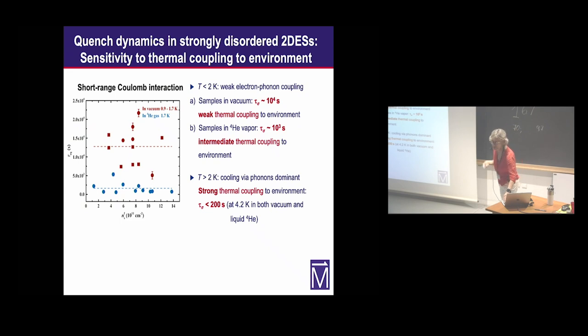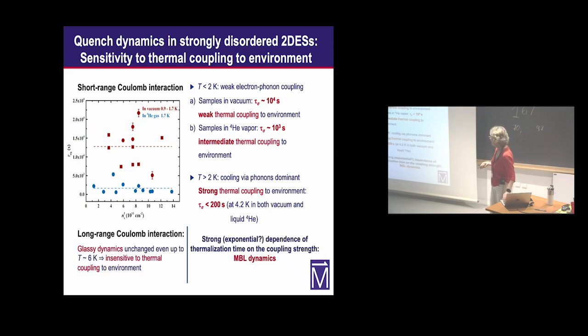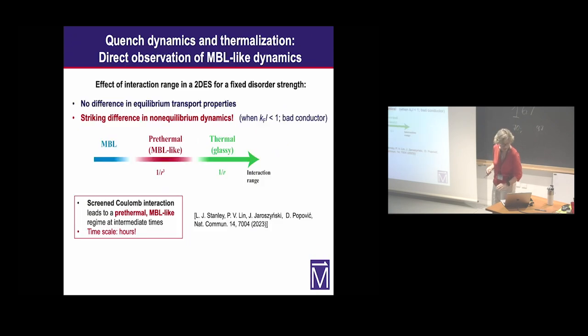So we have a very strong, maybe even exponential dependence on the coupling to a bath, in contrast to what we found in the case of glassy dynamics, where even at higher temperatures we do not see any change in the glassy dynamics. So what we found is that, yes?